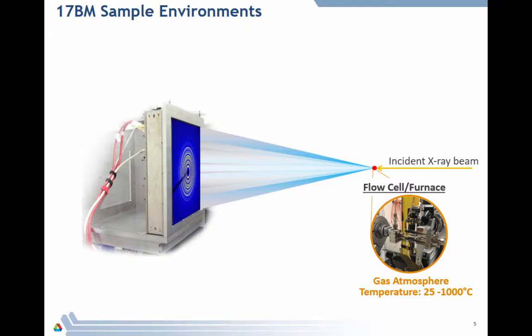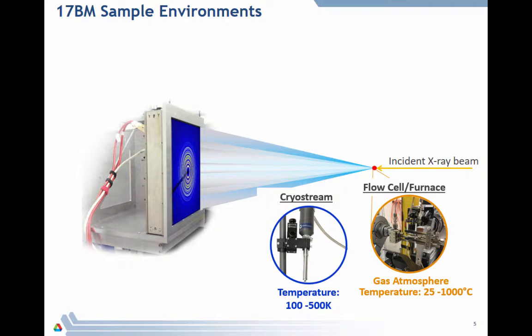It can be easily combined with a furnace, and therefore you can study your material within temperatures between 25 and 1000 degrees Celsius. Well, if you're interested in low temperatures, the furnace can be easily removed from this flow cell, and you can place on our beamline a cryostream, and therefore you have an opportunity to study your material at low temperatures between 100 and 500 Kelvin.